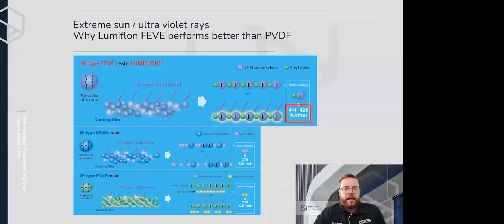Well, as you can see there at the top, you've got the FEVE Lumiflon and PVDF down the bottom. So the chemical bond between the carbon atoms and the fluorine atoms is too strong to be broken down by the sunlight. So this means that the polymer is not degraded by UV radiation from the sunlight. The alternating structure of the Lumiflon resin also increases the strength of other chemical bonds in the polymer, which protects the entire coating against degradation.